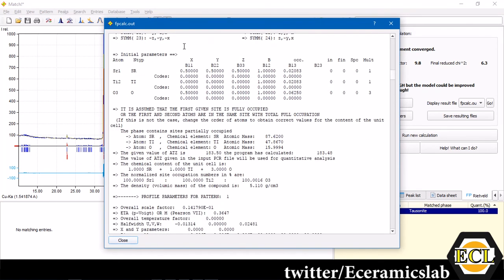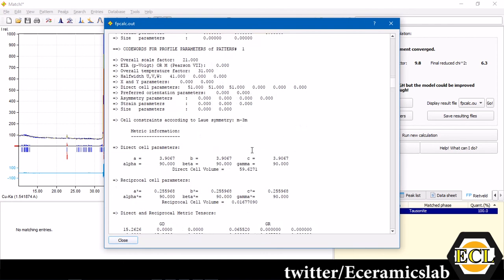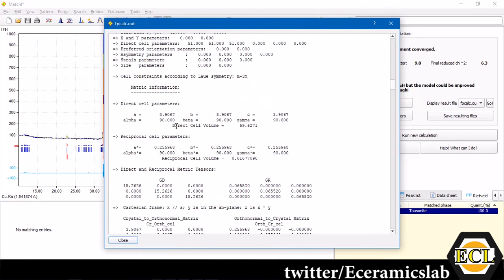You can find the X, Y, Z positions of strontium titanate for your system. And here are the lattice parameters. For our system, it is 3.9067. Since it is cubic, so A, B, C is going to be equal. And again, since it is cubic, alpha, beta, gamma is going to be 90 degree.